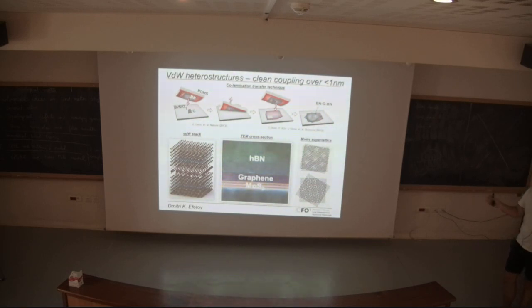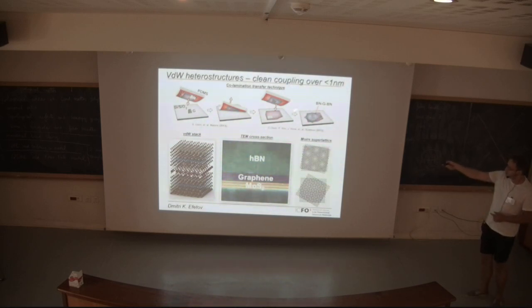Okay, so you don't get anything amorphous, you don't get anything dirty, but you really find regions where these interfaces are extremely clean, and then the hybridization between the layers is extremely, extremely good. So as you can see here, for example, between graphene and hBN, it's a relatively large region where you don't find a single defect. You don't find a single impurity at the interface. Okay, and last but not least, of course, because of the type of assembly we use here, one other thing is possible, which is not possible, for example, in MBE-grown heterostructures.